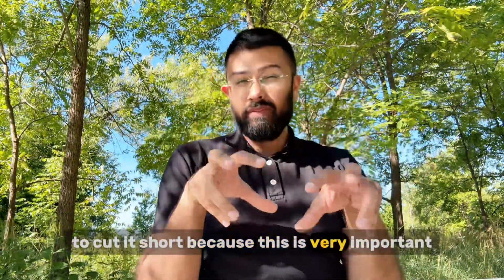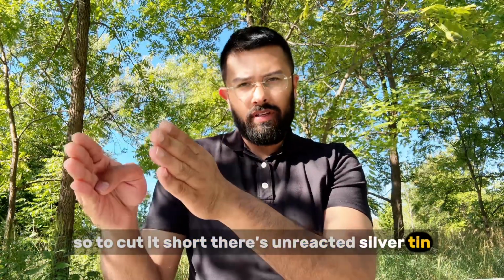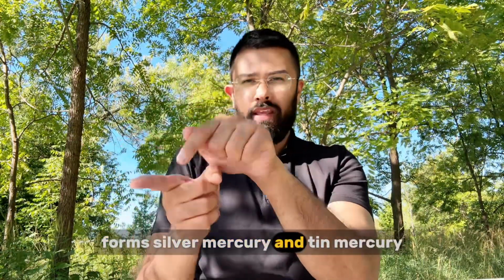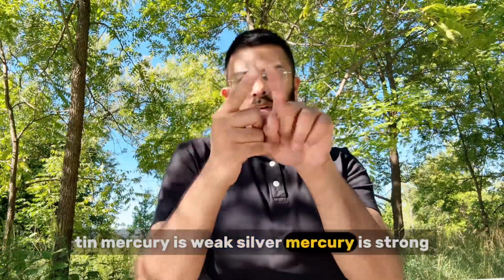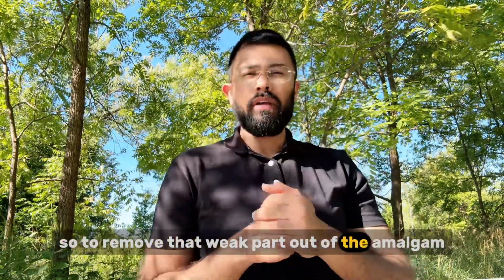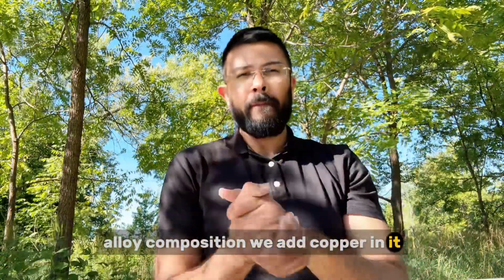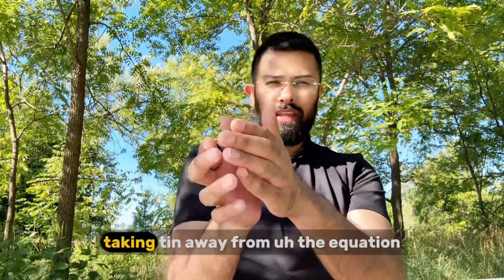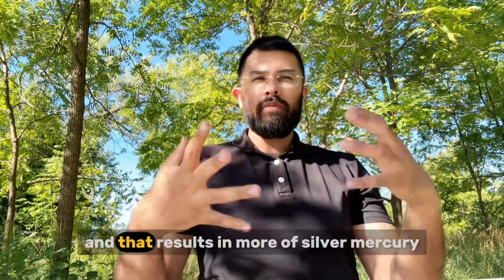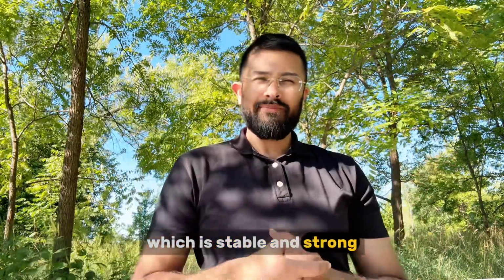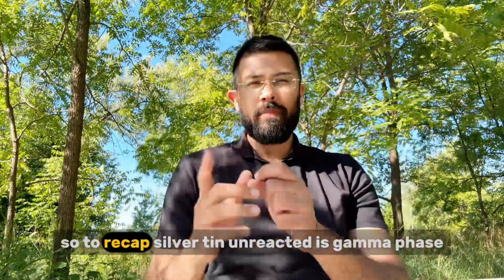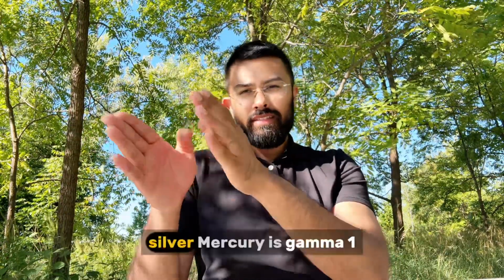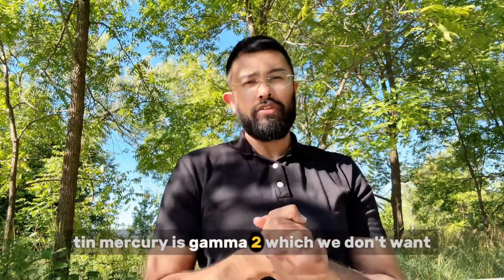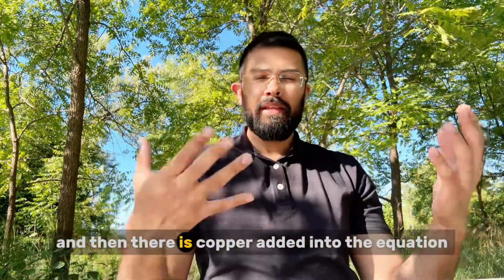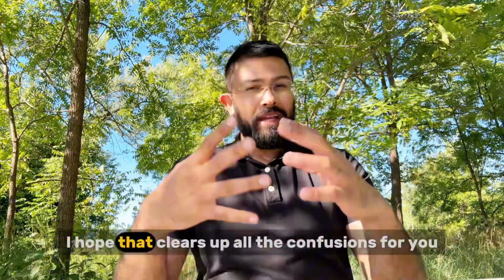Basically, to cut it short, because this is very important, this is why I am emphasizing a lot on it. So to cut it short, there's unreacted silver tin, which reacts with mercury, forms silver mercury and tin mercury. Tin mercury is weak, silver mercury is strong. So to remove that weak part out of the amalgam alloy composition, we add copper in it, and that basically reacts with tin, forming copper tin, taking tin away from the equation, and that results in more of silver mercury, which is stable and strong. I hope that clarifies all the concepts. So to recap, silver tin unreacted is gamma phase, silver mercury is gamma 1, tin mercury is gamma 2, which we don't want, and then there is copper added into the equation that forms the eta phase. I hope that clears up all the confusions for you.